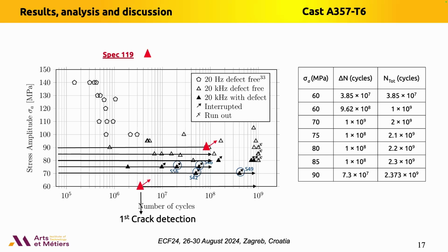And we didn't observe any crack propagation again. So finally, we decided to increase the stress level step by step. And finally, we obtained not crack propagation, but the initiation of a new crack elsewhere in the microstructure, in fact, behind the defects of another crack. And finally, we observed that at 10 to the 8 cycles. So, it means the specimen history is all these load cycles.